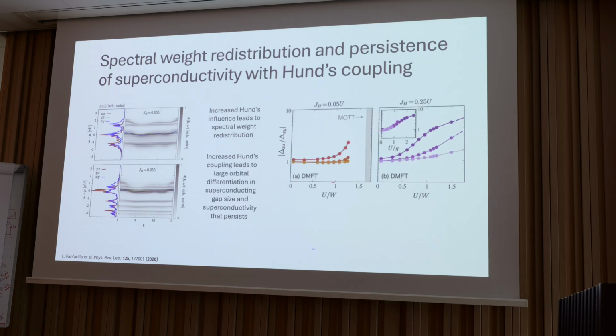And so with that, they do this superconductivity model, which I think they're only considering intraorbital pairing, but they see that this increased Hund's coupling leads to large orbital differentiation in superconducting gap size and also superconductivity that persists for more parameters here. So low Hund's coupling, higher Hund's coupling. And so we see from these papers that Hund's coupling may help to explain the anisotropic gap and persistence of superconductivity with hole doping.